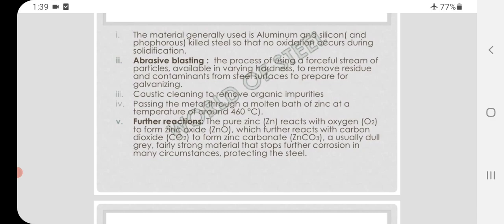Abrasive blasting: the process of using a forceful stream of particles available in varying hardness to remove residue and contaminants from steel surfaces to prepare for galvanizing. Caustic cleaning to remove organic impurities. Passing the metal through a molten bath of zinc at a temperature of around 460 degrees Celsius.